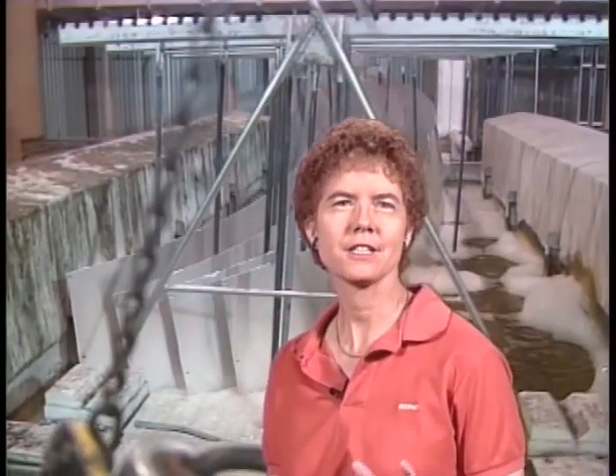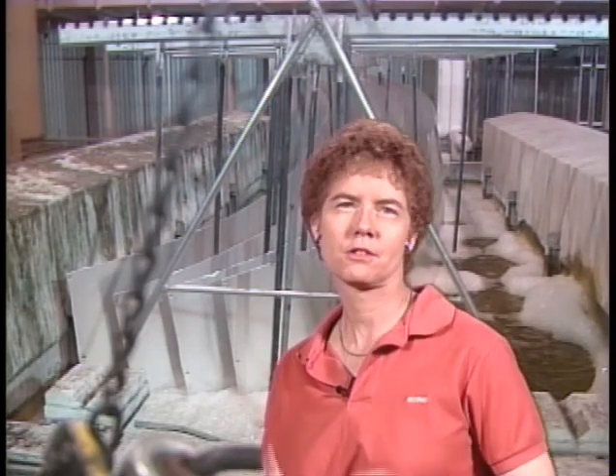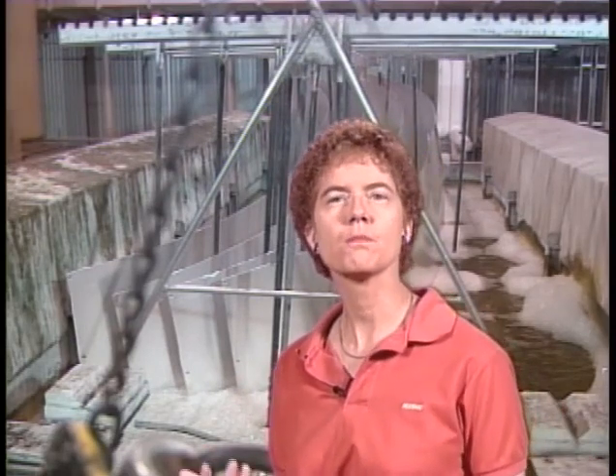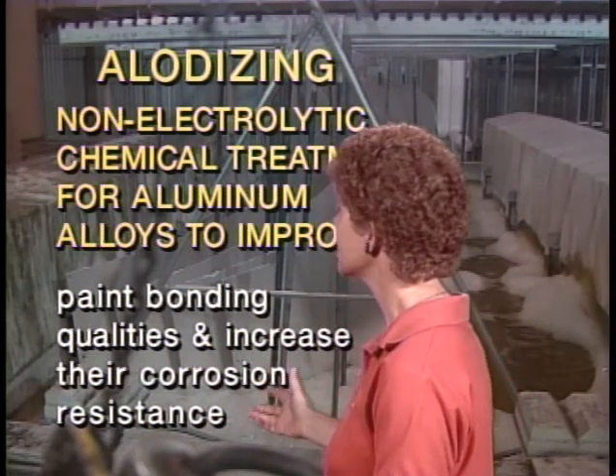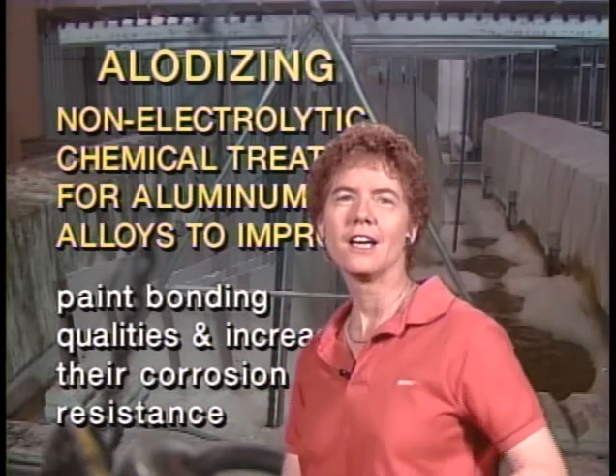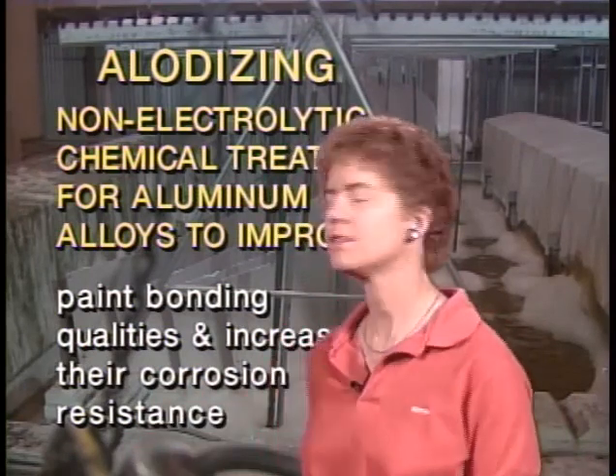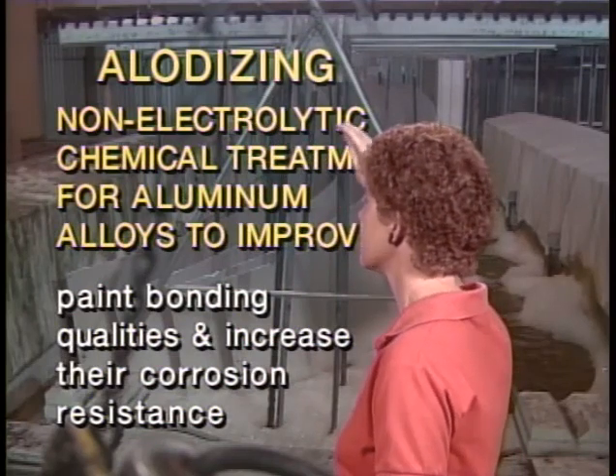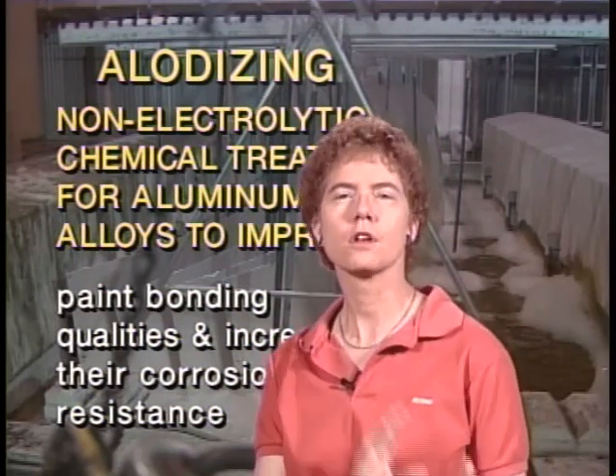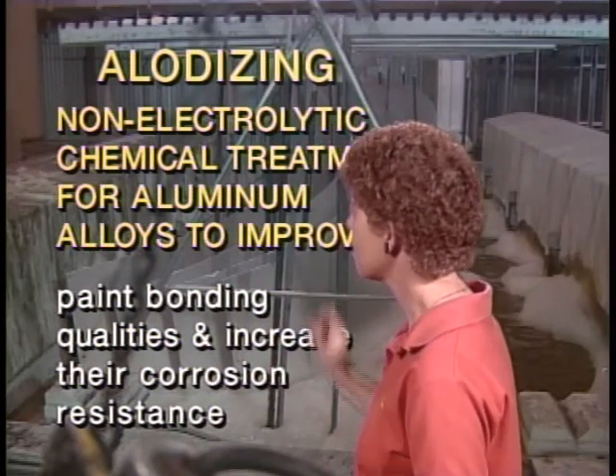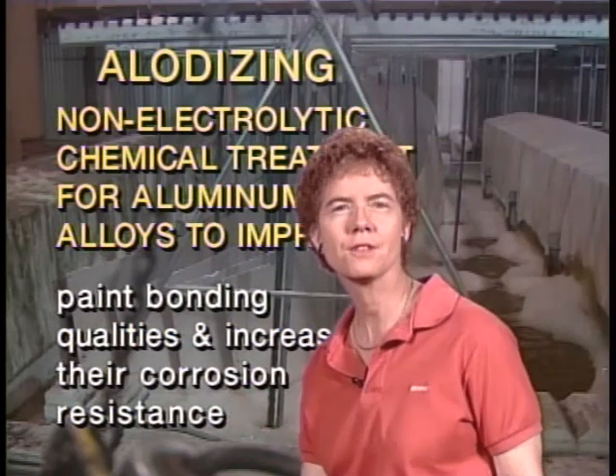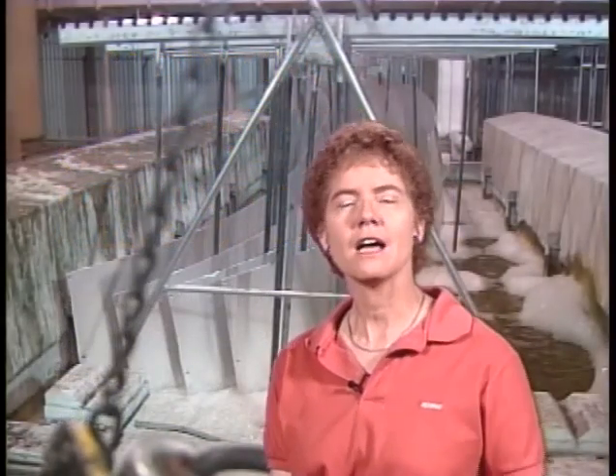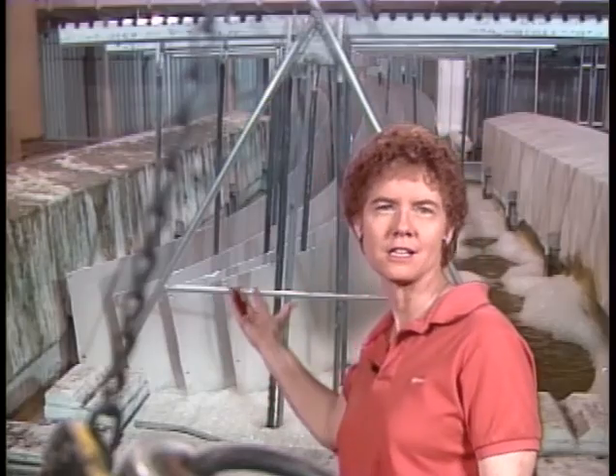Now that chemical surface treatment that you're seeing here is called alodizing, done a lot of times with the trademark product Alodine, and it's a non-electrolytic chemical treatment for aluminum alloys, and the purpose of it is to improve the paint bonding qualities and also to increase the corrosion resistance. It's very easy to get alodizing and anodizing confused, but alodizing is a non-electrolytic treatment. It is a chemical surface treatment for aluminum alloys, and it does improve both the paint bonding qualities and the corrosion resistance of the aluminum alloys. You also need to know that alodizing, or Alodine, is applied to aluminum alloys by dipping them as you're seeing it done here.